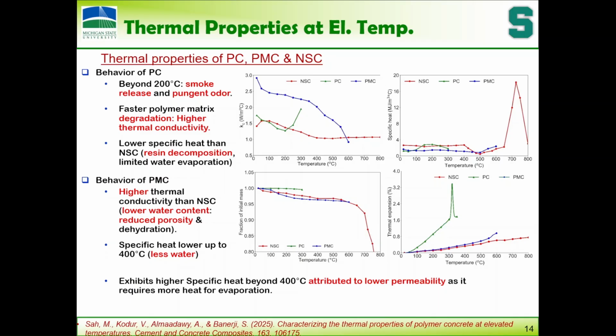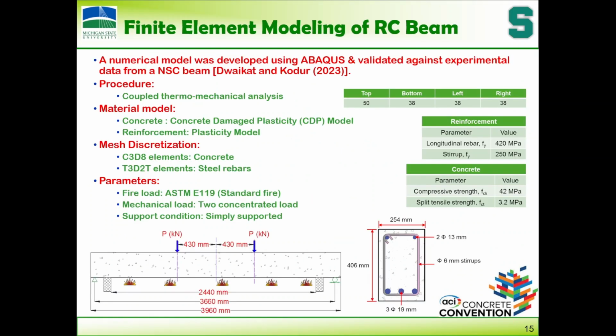But PMC, because it has less resin content, we could take up to 600. Ideally, in fire design, you need up to 800 degrees for structural design in buildings. In bridges, you need up to 1000 degrees. So even doing the test is a problem. Then, very quickly, I'll show you some of this.